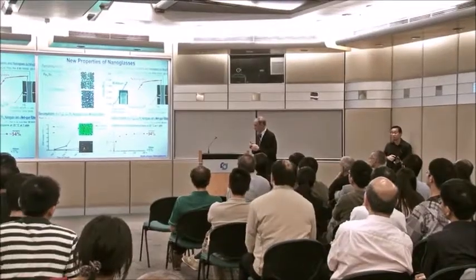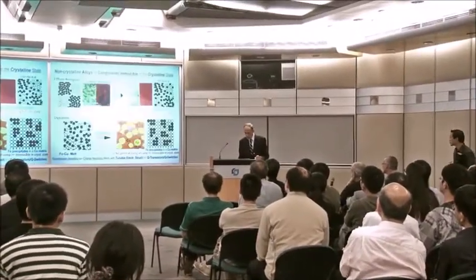Can you tell us why nanoglass has much better ductility? Do you know mechanistically why the ductility is much better? Right. This is what we see in the computer simulation. When we take a glass on the computer and pull it, molecular dynamics, then you get a shear band and the thing fractures. And what we see when we pull a nanoglass is that out of these interfaces the shear bands come out, and then they run across the glassy region, and then they end up in the next interface.